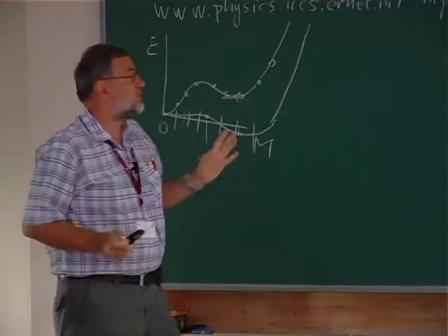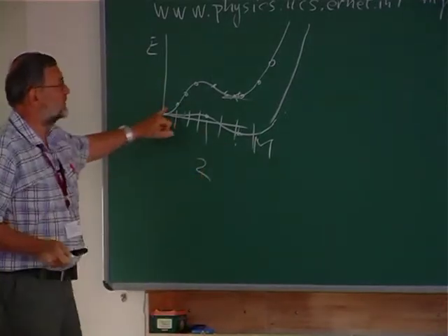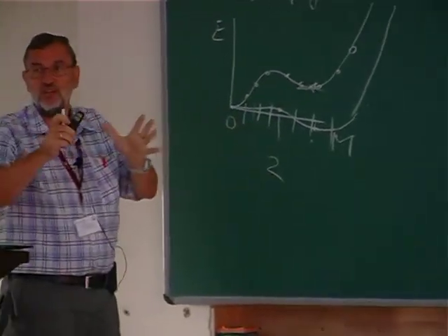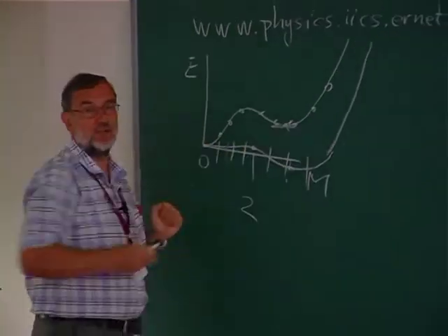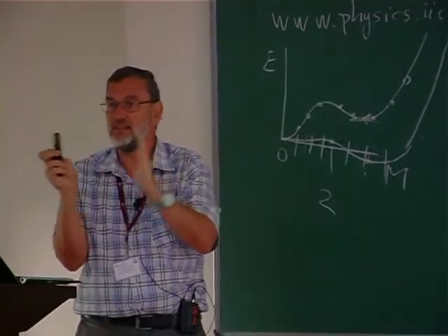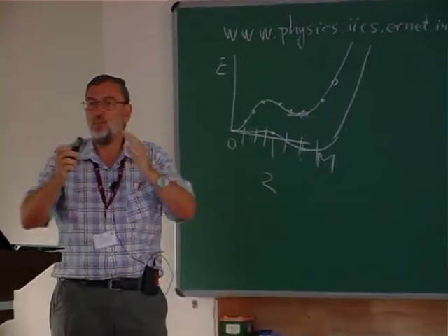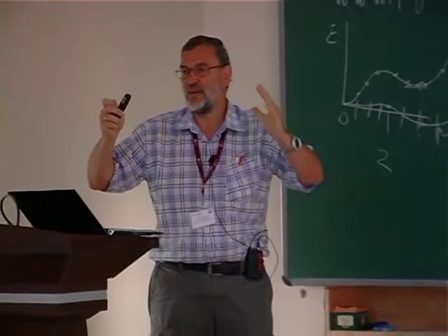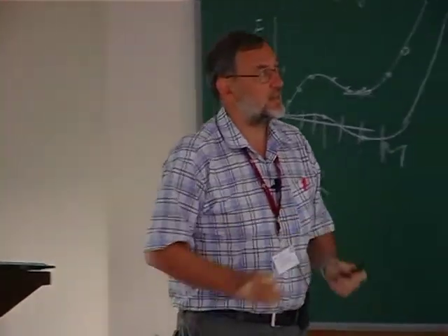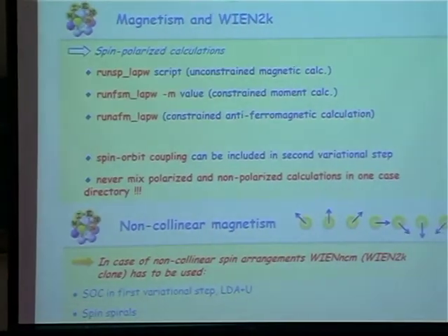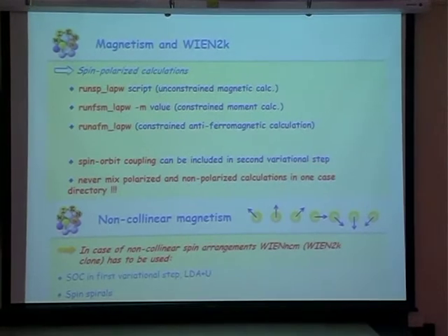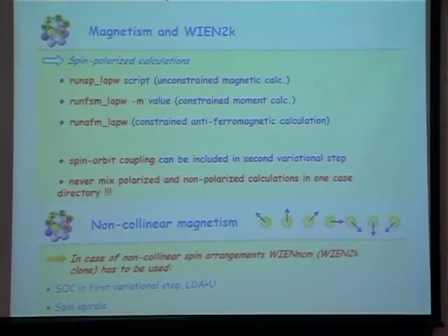And this can be explained with such a transition that with changing volume, it would change the magnetic state from non-magnetic to magnetic, and that would have a slightly different volume. And that compensates the thermal expansion and shrinks it again. So things like this, for this run FSM is very useful. Eventually, one could also do antiferromagnetic constraints or things like this.